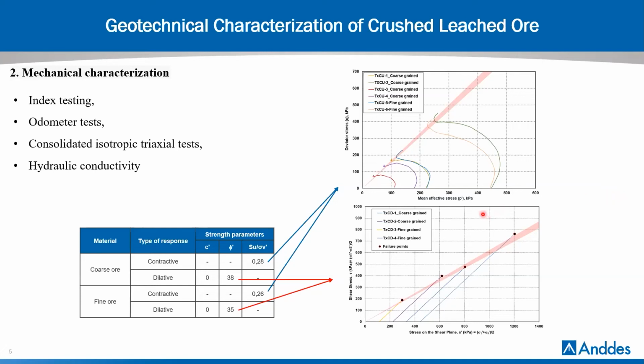The undrained strength envelope was initially estimated from p-q stress paths derived from the CU triaxial tests, as shown in this figure. Then the trends in the data were verified with a simple critical-state-based expression for a normalized undrained strength, which was found to vary within 0.26 to 0.28.